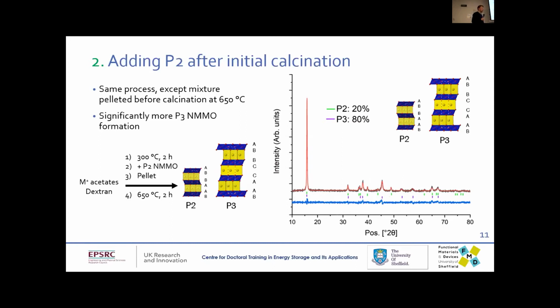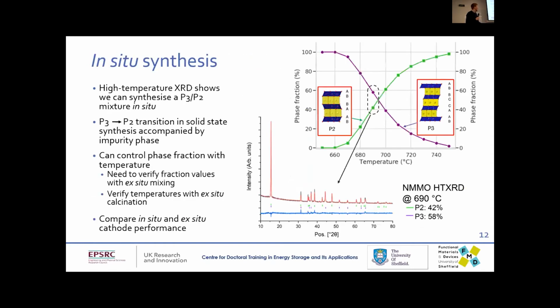So what I think is happening is that as the P3 crystal is growing, there is some sort of interfacial interaction between the growing crystal and the P2 crystal that was already in there that's causing the P2 crystal to break down, which is quite interesting. I'd like to dig into that a little bit more. But the key thing here is that I'm not getting this one-to-one ratio that I was aiming for at the start. So I'm going to try and make this essentially in one step by finding this midpoint. That's what this next slide is.